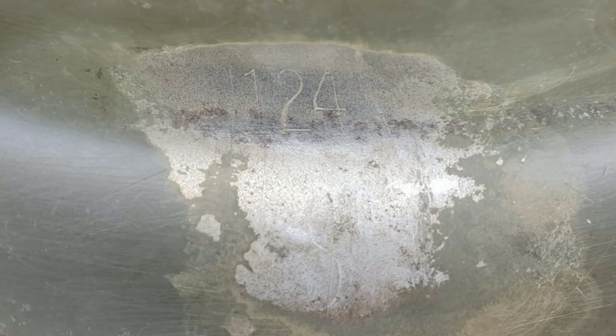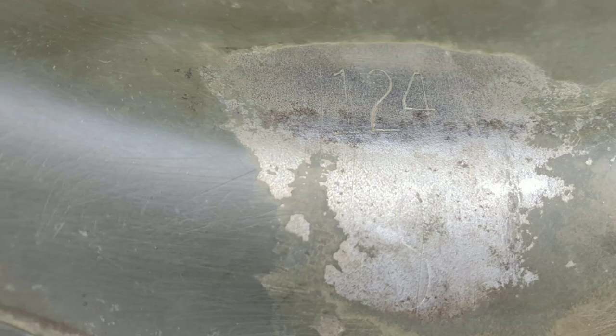When tests were authorized, the pressing concern would receive the sheets from the mill, assigning the heat a standard lot and lift designation with the addition of a number after the alpha suffix to segregate the lot from the control. An example of this was a test performed to determine the effect of edge annealing on age cracking in the helmet visor. Discs from Sharon Steel Company heat number 73,191 and Schluter lot and lift number 213BS were pulled and separated, sheets with the lot and lift number stamp in front of the lot number, into two test groups, 213B2S and 213B3S. 213B2S was the control and was manufactured under current standards while group 213B3S had the brim annealed.